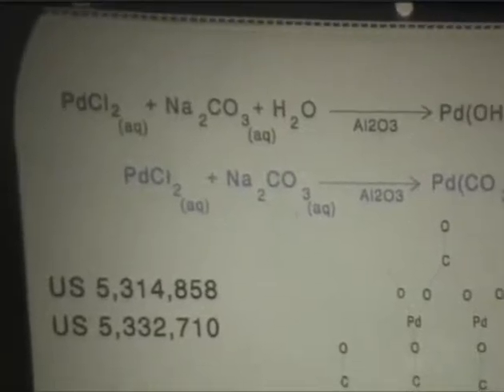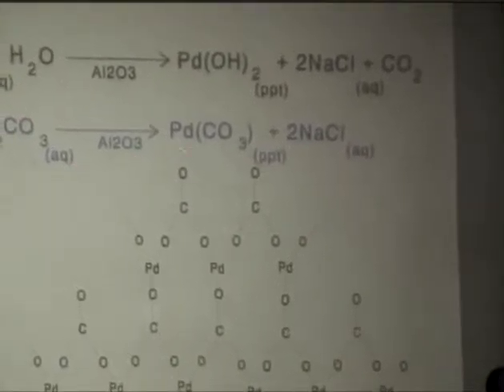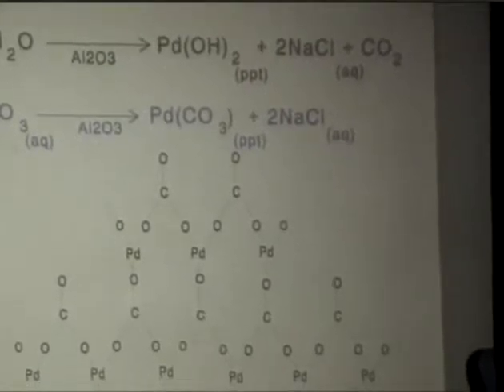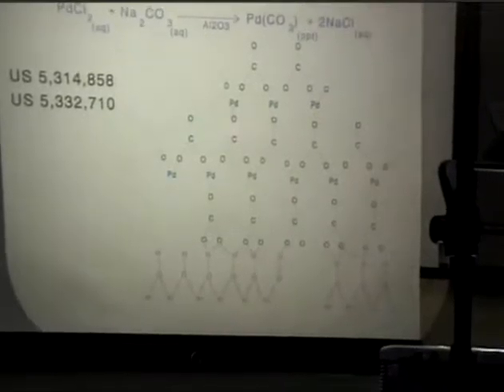Whereas we thought it'd be kind of interesting if that didn't happen, and what would happen as opposed to that would be if you just make the carbonate. The reason that would be interesting is if you can imagine some type of palladium carbonate, as I sketched out here, and this is completely imaginative at this point, that once you reduce this to get the palladium metal, and that's in fact what we do want for the catalysis, you would get all sorts of defect sites and problems as this carbonate collapsed into the zero valent metal.